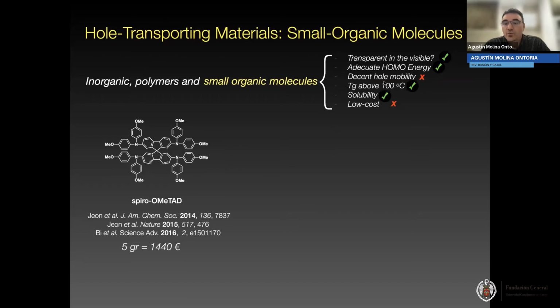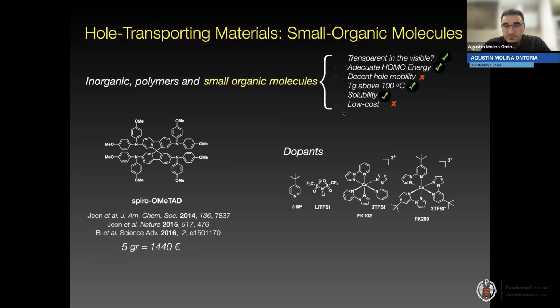So in order to improve the hole mobility, some of the hole transporting materials need dopants. This could be the lithium salt, and this cobalt complex, which are used to improve the mobility of the hole transporting materials. And TBP is a morphology controller.